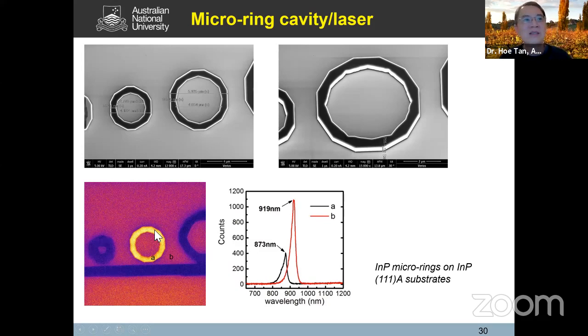Okay? And this is shown here, this is a cathodoluminescence. So this is not lasing yet, but we are still working on it to improve essentially the optical cavity, the quality factor of the ring. And furthermore, this is grown indium phosphide on indium phosphide. So we don't have a good refractive index contrast.